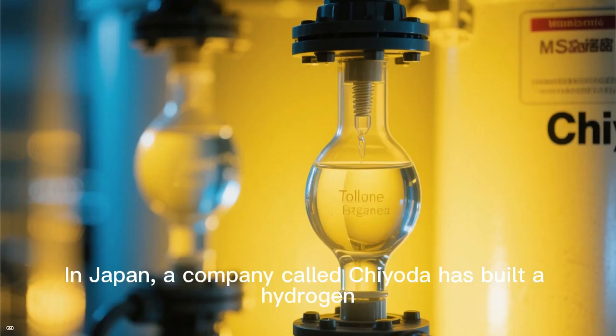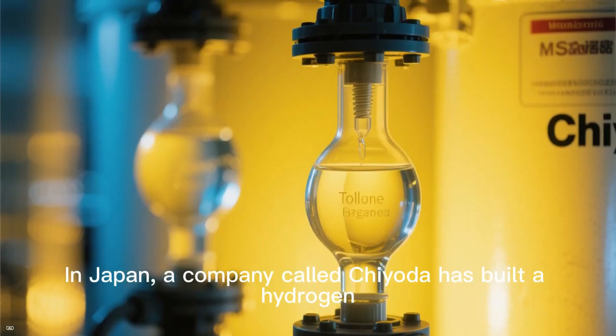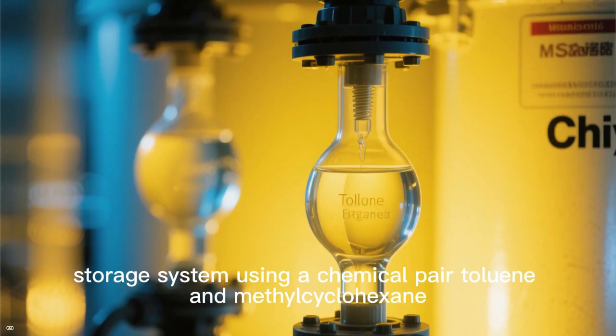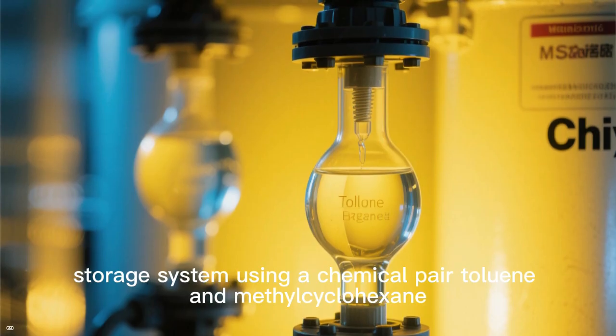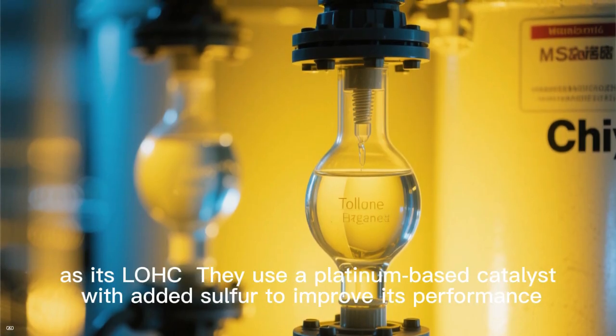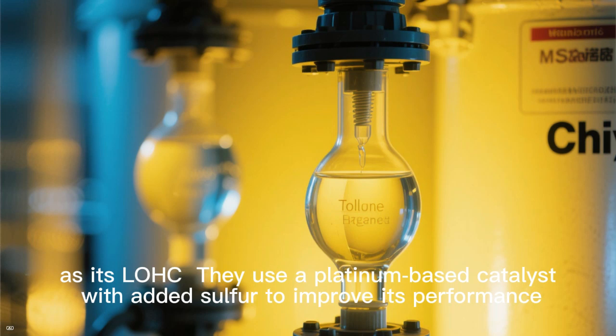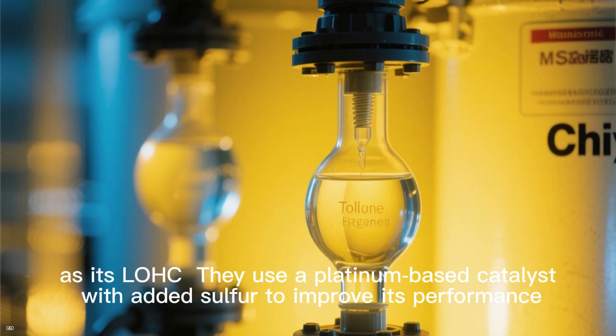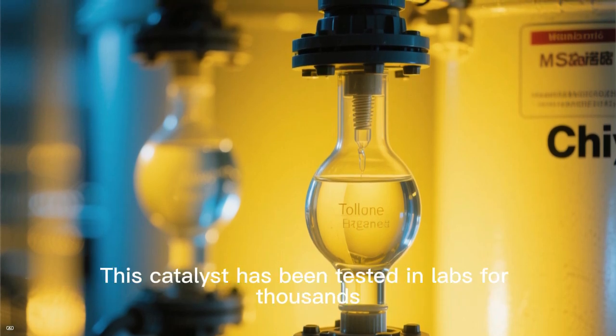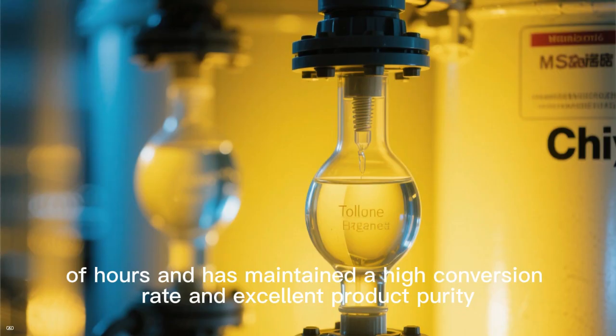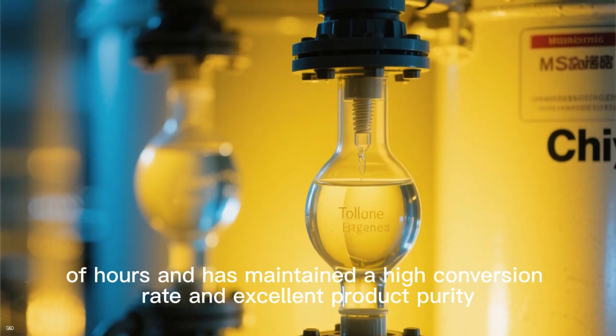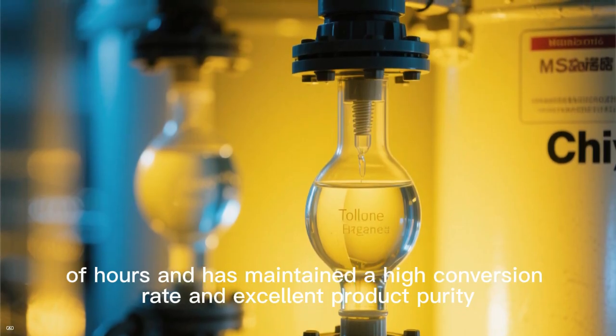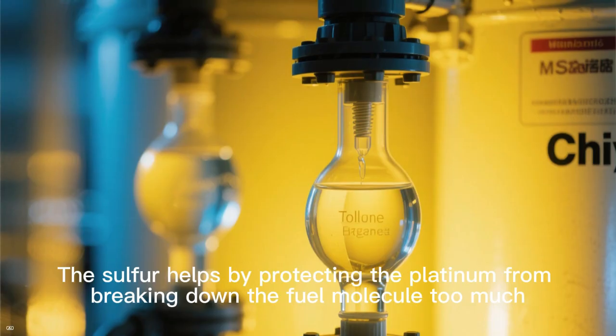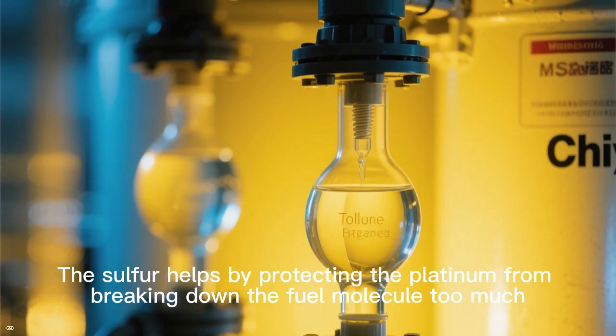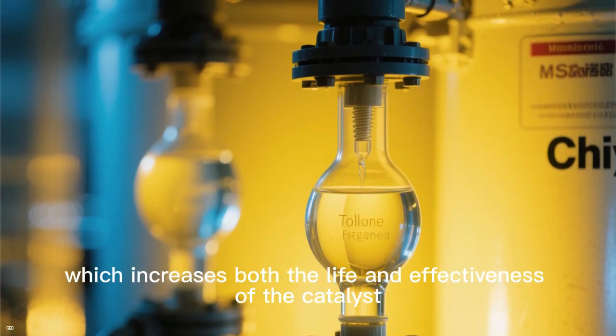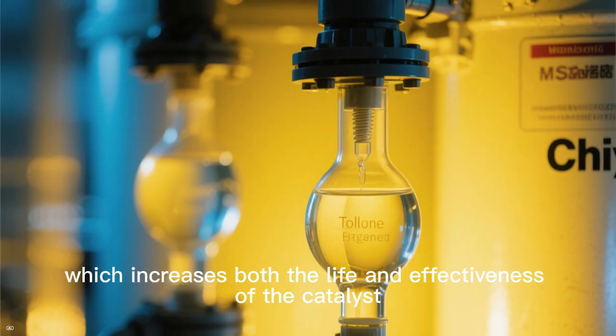In Japan, a company called Chiyoda has built a hydrogen storage system using a chemical pair toluene and methylcyclohexane as its LOHC. They use a platinum-based catalyst with added sulfur to improve its performance. This catalyst has been tested in labs for thousands of hours and has maintained a high conversion rate and excellent product purity. The sulfur helps by protecting the platinum from breaking down the fuel molecule too much, which increases both the life and effectiveness of the catalyst.